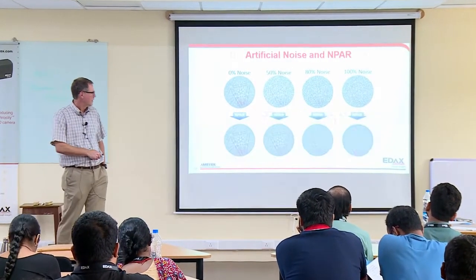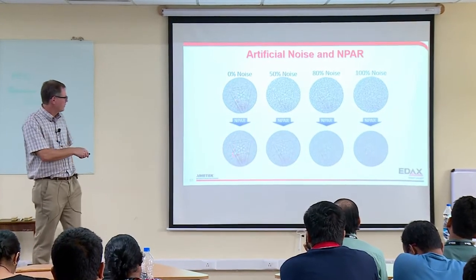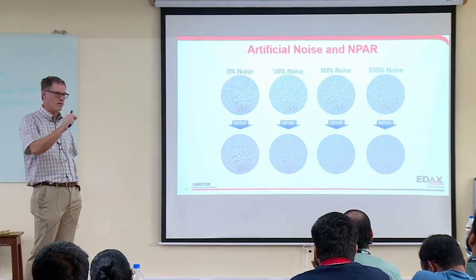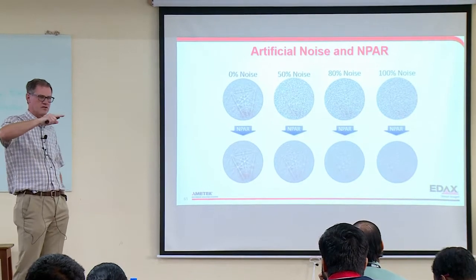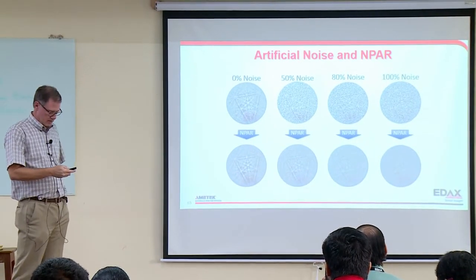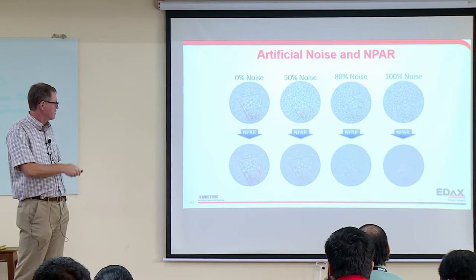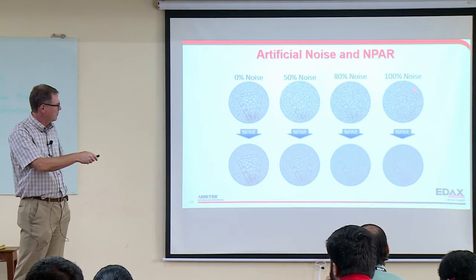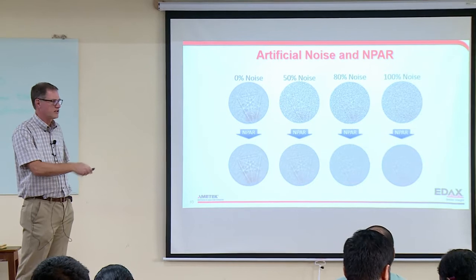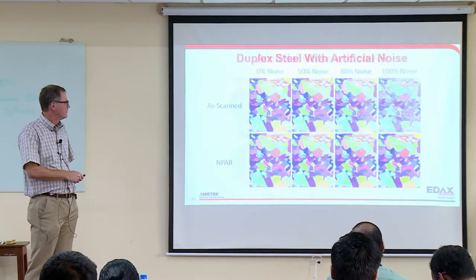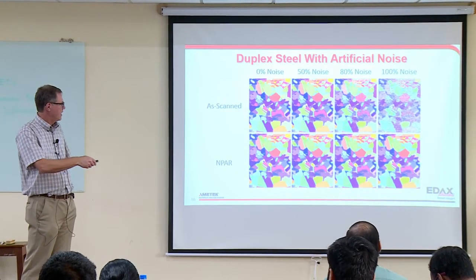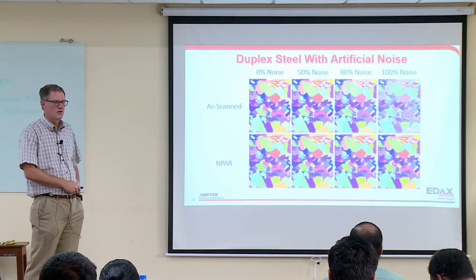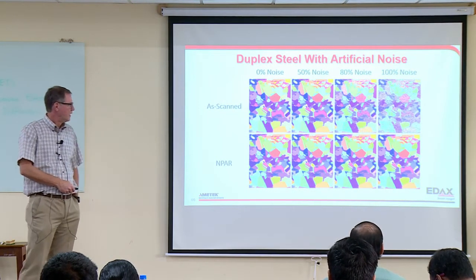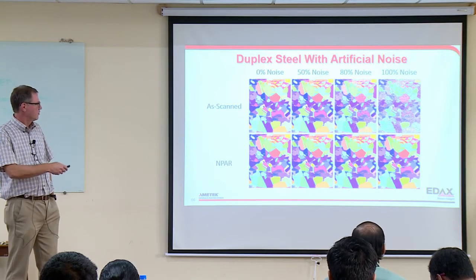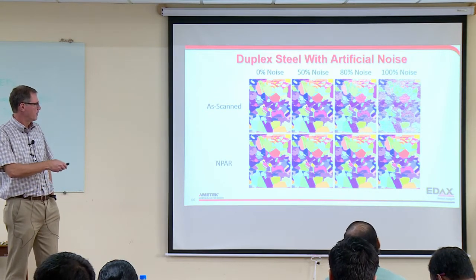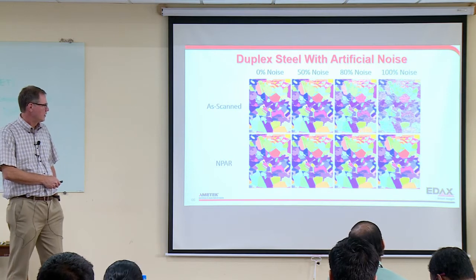So now I apply this NPAR algorithm. So I take the pattern at a pixel, take the pattern from all the neighboring pixels, and average them together. And so you can see this is a big improvement in the pattern quality, and from something where you don't see any pattern, you actually can see a pattern now. And so as scanned and NPAR, huge, huge improvement. And so we're using this to deal with noise when we have really poor patterns. And it really works well.